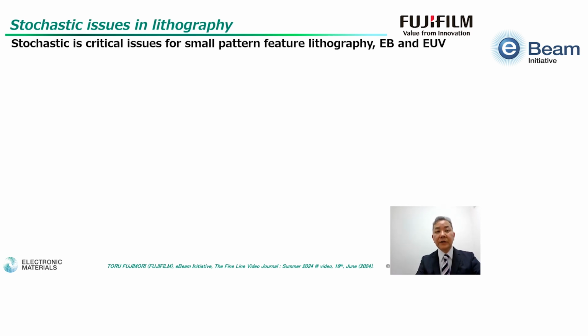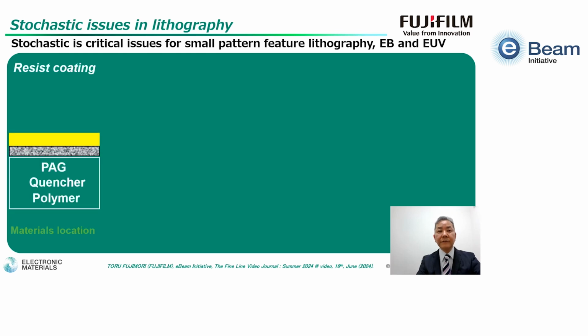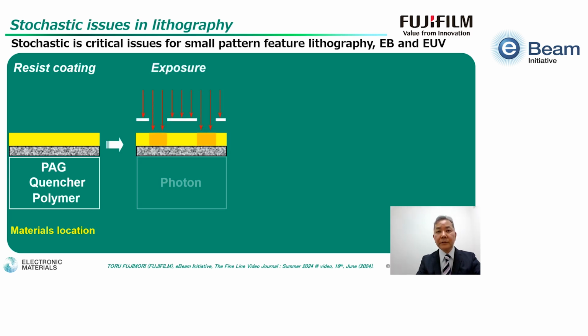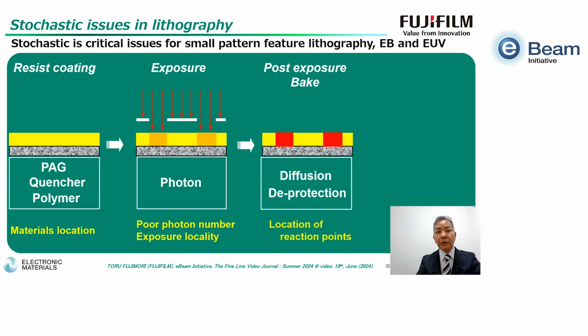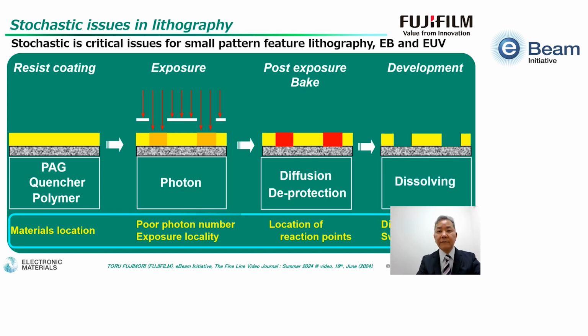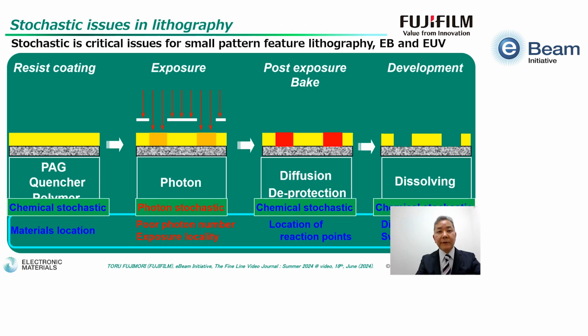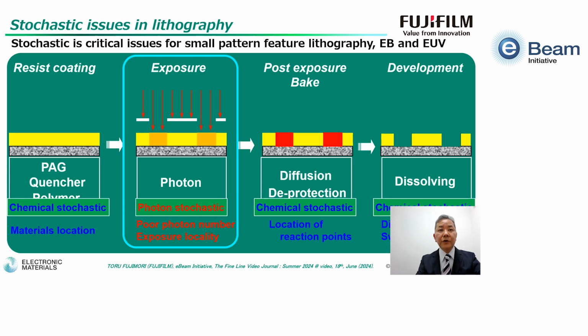Stochastic issues in lithography were classified, as shown here. The first step, resist coating, observed material location randomness. During the exposure, due to poor photon number, the exposure locality is observed. And during the post-exposure bake, location reaction randomness, and during the development, dissolving locality and swelling behavior. Classified in two categories: the first one is photon stochastic and the other is chemical stochastic. Talking about photon stochastic first.